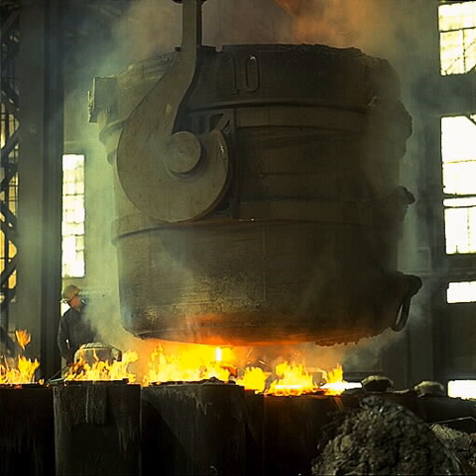Copper is added in the ladle or in the furnace, on the order of 0.5 to 2.5%, to decrease chill, refine graphite, and increase fluidity. Molybdenum is added on the order of 0.3 to 1% to increase chill and refine the graphite and pearlite structure. It is often added in conjunction with nickel, copper, and chromium to form high-strength irons.